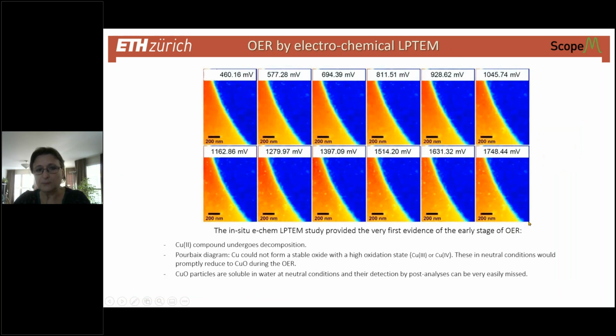Right now, we have studied the oxygen evolution reaction reproducibly, quite a few runs, quite a few days, months, as usually you work to confirm the data, and we conclude that the copper-2 compound does undergo decomposition at the very early stages upon application of potential. Now, relying on a Pourbaix diagram, we think that copper could not form a stable copper oxide with a high oxidation state, copper 3 or copper 4, because in the neutral solution, these small copper 3, copper 4 oxidation state particles will reduce to copper oxide.